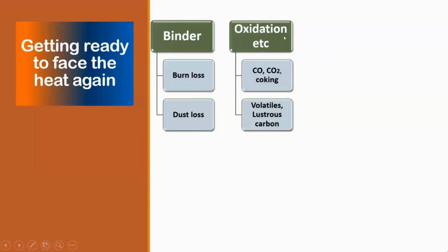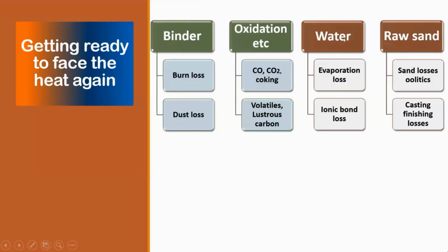Then there is an oxidation loss, like some of the carbons are burnt as carbon monoxide or carbon dioxide. Some carbon will get into a form of coke. Then the volatile materials can volatilize and sometimes produce lustrous carbon also. Then you have water which is lost due to evaporation, and the combined water, the ionic bond, is lost due to extreme heat.